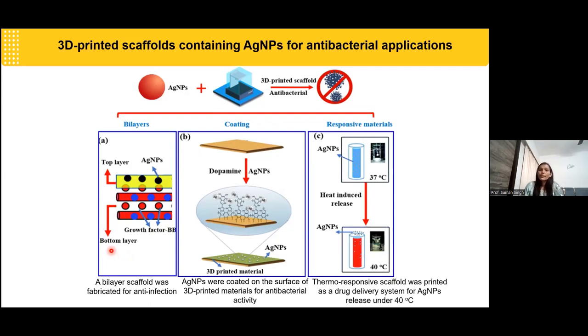For the coatings, anti-fouling coatings, these silver nanoparticles play a major role. Responsive materials also, for example, part C, it is temperature sensitive: with the change in temperature, the silver nanoparticle embedded 3D structure can change color. For example, in this figure, we can see that at 37 degrees it is blue in color, but at 40 degrees it has turned red. So it is a thermoresponsive material which can be used. Next, please.